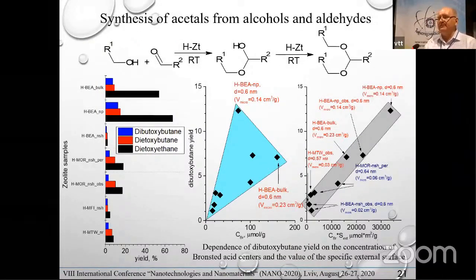One more process is formation of acetals from alcohols and aldehydes. We can see different activity, especially high activity when using a small substrate with formation of diethoxyethane. In the case of a larger substrate with formation of dibutoxybutane, the activity is lower. However, we can see a very interesting dependence of the yield of these products on some superposition of external surface and concentration of acid centers.